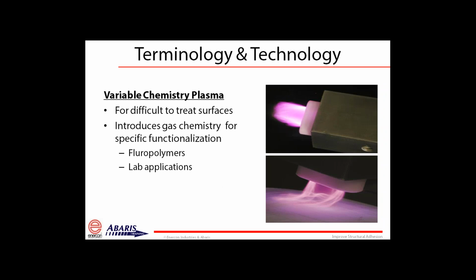Variable chemistry plasma is a technology that we'll introduce when we tend to find problems either with blown arc, blown ion, or the next technology we'll talk about, flame, when we're having difficulty getting treatment on those. With variable chemistry, what we're going to do is introduce a process gas. With blown arc and blown ion technologies, what we're really ionizing is the oxygen that comes in a supplied compressed air line. With variable chemistry, we add that process gas and ultimately functionalize the surface a bit differently.